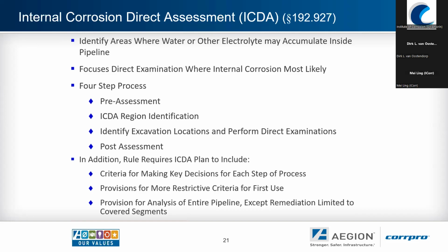Closer to production systems, it's also possible that there's water carryover from the dehydration process, or if there's again, interruptions in the dehydration that allows wetter gas into the system. What we want to do is really focus in our attention along this pipeline to the areas where the internal corrosion has the highest likelihood, following the four steps again, as we did with the other direct assessment protocols. If an operator has included ICDA into their integrity management plan, there are a few more pieces that are required by the federal regulators.